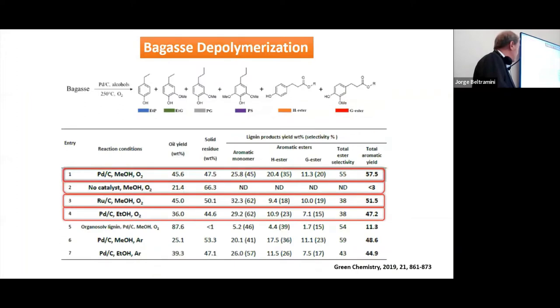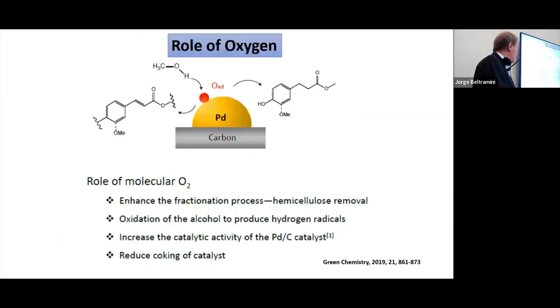How we can justify this? This is the result. You see here we work with different catalysts and no catalysts, and the total aromatic yield and the aromatic ester, the H and the G ester, is very high. And also here we use oxygen, we don't use hydrogen. Why is the oxygen important here? Very simple, because we found that oxygen enhanced the fractionation of the process. The oxygen allowed us to remove the hemicellulose.